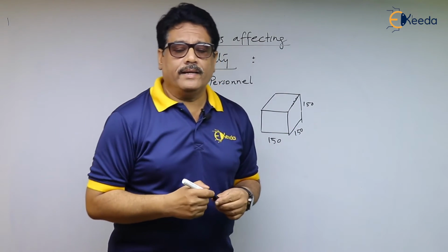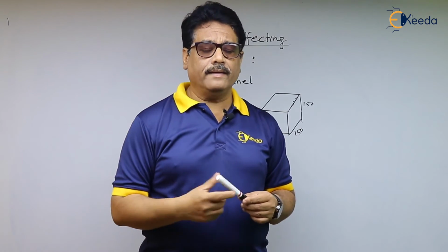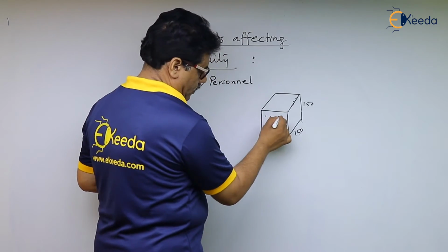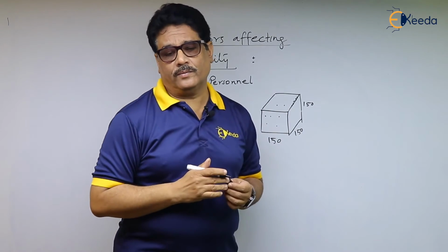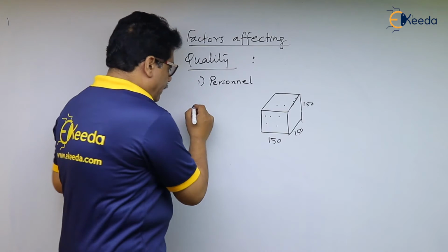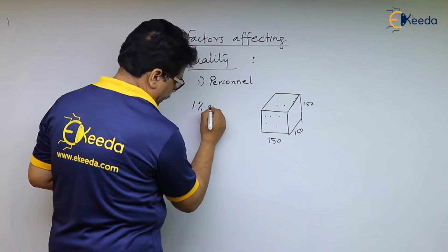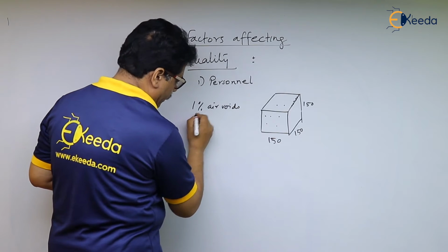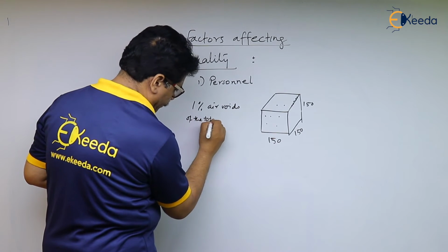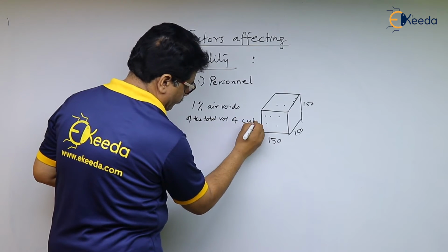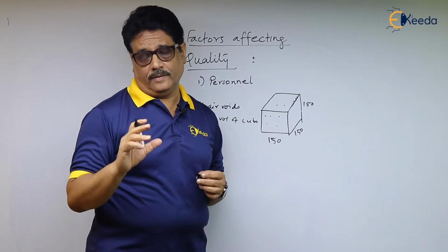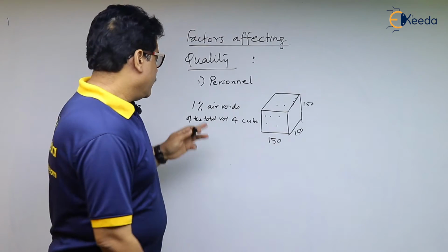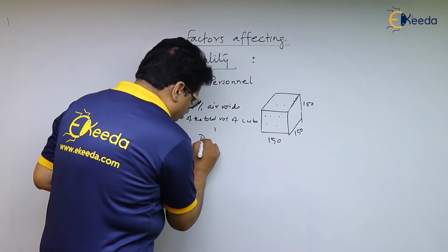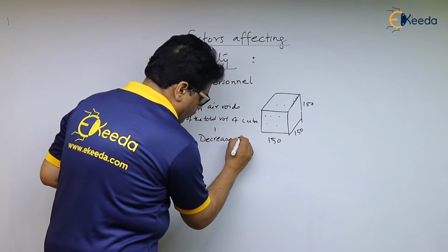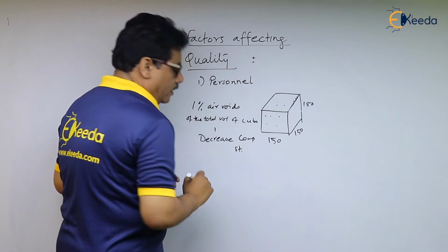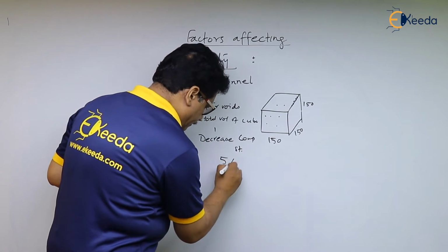or again when the vibrations are not uniform, then there may be air voids on the surface of the concrete. Now, even 1% air voids, 1% of the total volume of the cube, if 1% of that volume is air void, then this is responsible for decreasing the compressive strength of concrete, and that too by 5%.